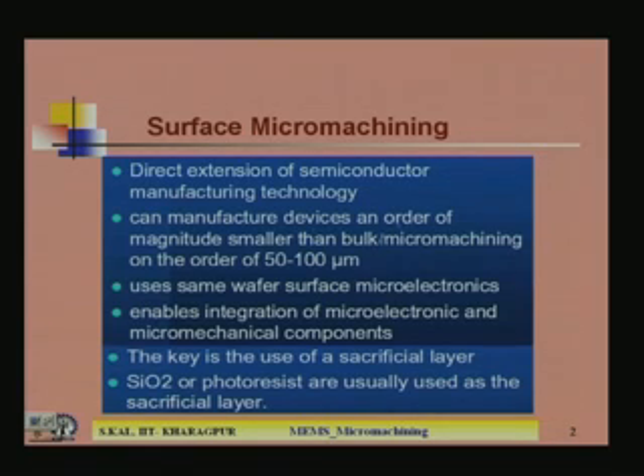Next point is it can manufacture devices an order of magnitude smaller than bulk micromachining, on the order of 50 to 100 micrometer. That means you can make the devices much smaller, one order smaller in dimension. The reason is if you go for deeper etching, then automatically there will be some slant portion, which is not etched straight, like a pyramidal structure. So, for that you have to allow certain space. But if you go for a very small amount of etching, in the range of say 2 micron or 3 micron, you do not have to spend that much space on the silicon surface. In that way you can reduce the complete area of the device if you go for surface micromachining technology.